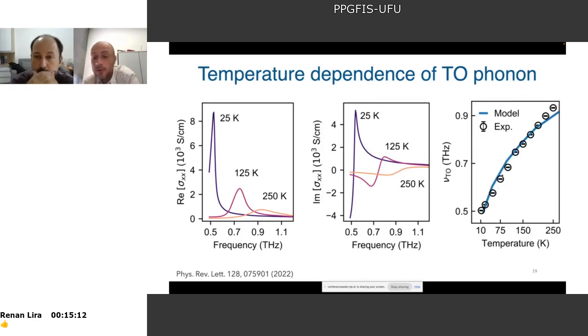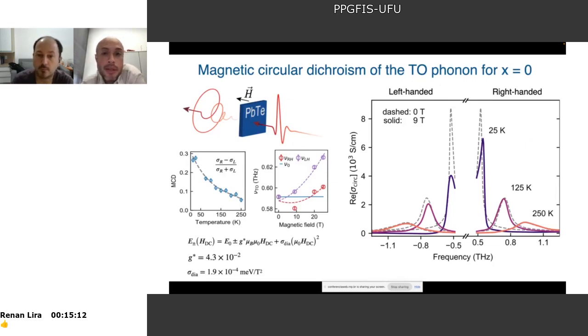Here there is a fitting of the frequency of the phonon as a function of temperature. This model includes anharmonicity. The TO phonon modes in this material are strongly anharmonic, and this is why this material is very important for thermoelectric applications. In this case, lead telluride is not ferroelectric. The phonon mode only decreases. As you can see here, the frequency only decreases, but there is no turning point. It cannot become ferroelectric. Okay, let's keep that point in mind.